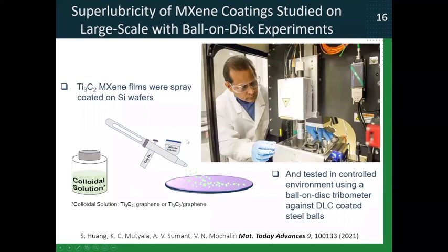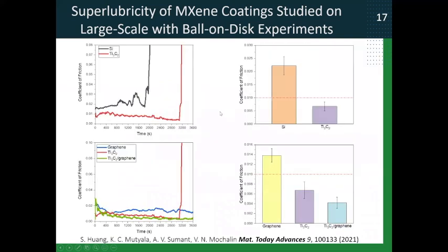So in this work, we measured tribological properties of MXene films deposited by spray coating. Here's the schematic. We tested them using a ball-on-disc tribometer against DLC-coated steel balls in a controlled environment. Now, these are the data which we observed when we tested these films in dry nitrogen atmosphere.